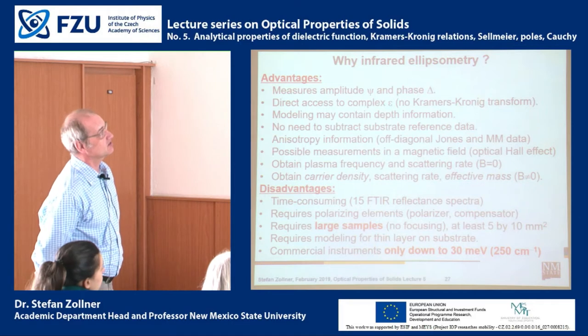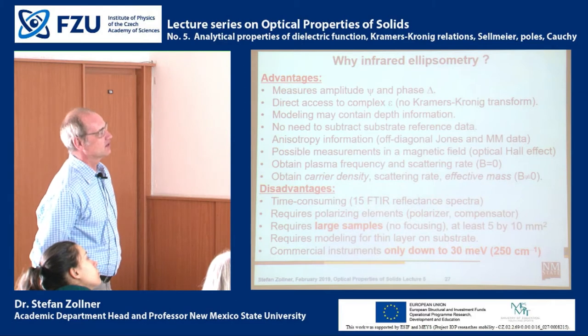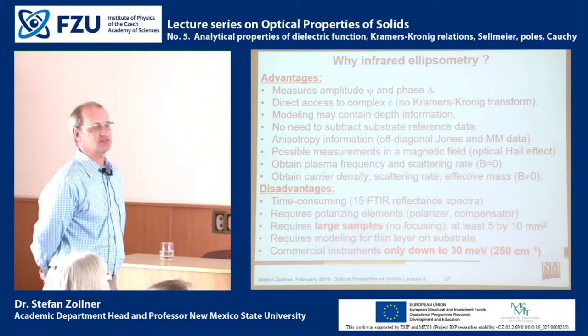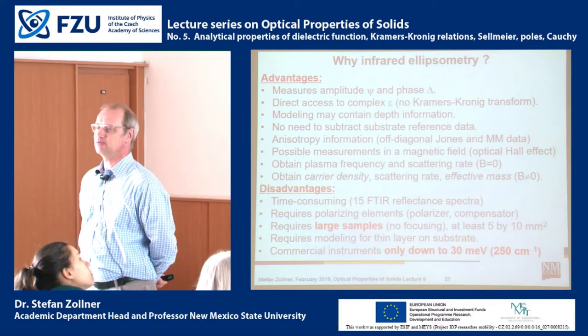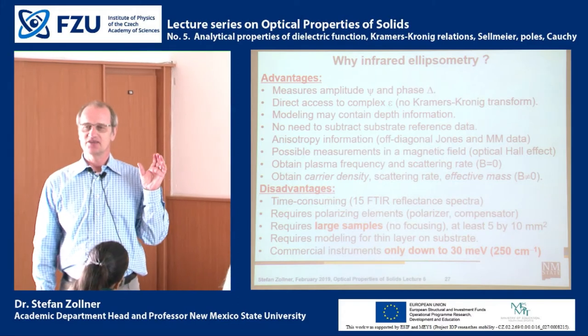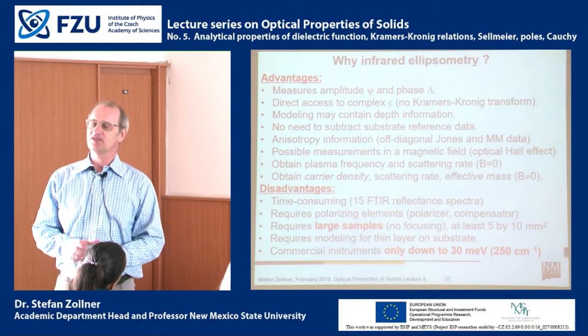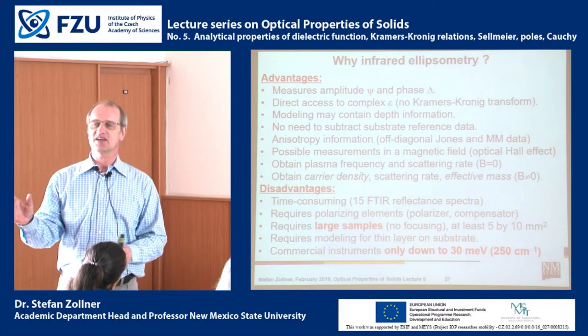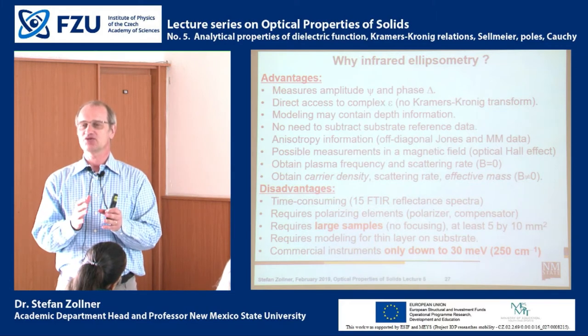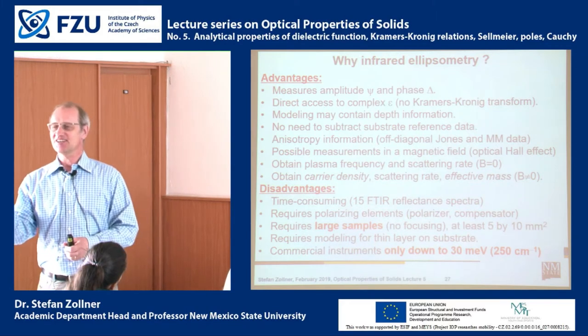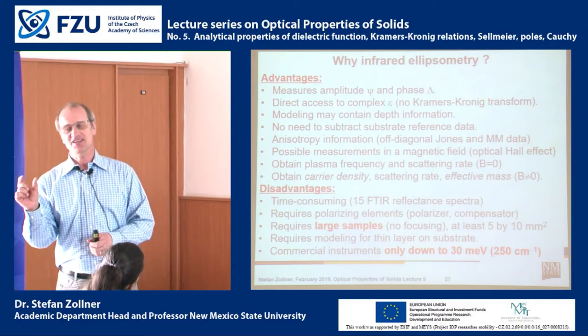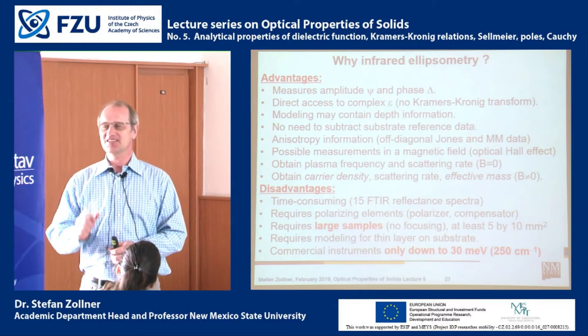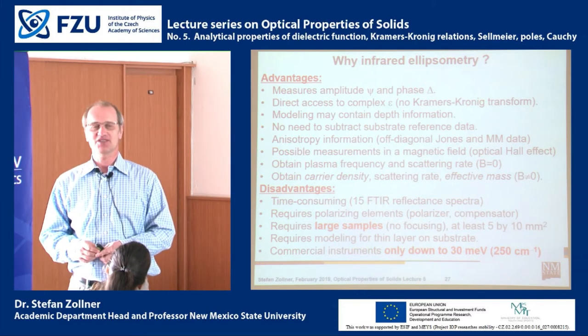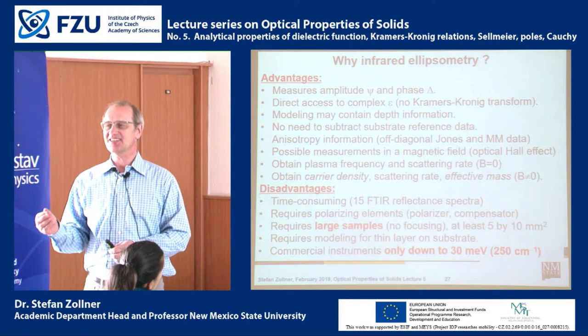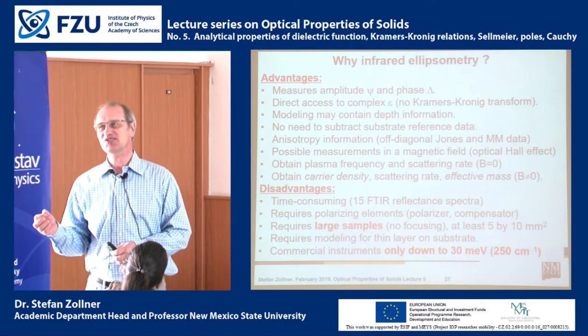Ellipsometry, obviously, because it's ellipsometry, we have information about film thickness, so we get depth information. Sometimes what people do with infrared spectroscopy is that they have a film on a substrate, so you measure the transmission of your substrate, and then you measure your transmission of the film plus substrate, and then you just subtract the two, and you call that the transmission of your film, and therefore you calculate the absorbance of your film, and you interpret it that way. Unfortunately, that's done quite often, especially by chemists.